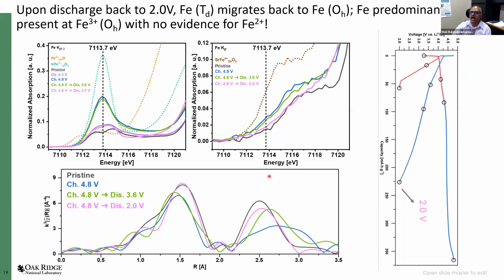So on the other hand, when you discharge and look at the iron, what we find is that the iron that had already migrated to a tetrahedral site comes back to the octahedral site, and most of the iron is present as Fe3 plus now in the octahedral site. We see little or no evidence for the formation of Fe2 plus. This is again a very interesting observation because in literature, many iron materials' performance is supposed to be compromised by the formation of Fe2 plus. We don't see that in this material, so we think that there is some scope by which we might be able to engineer a better material and utilize the iron 3 plus 4 plus couple, which occurs at a higher voltage and can give us higher energy density. That is something that we would be doing in future.